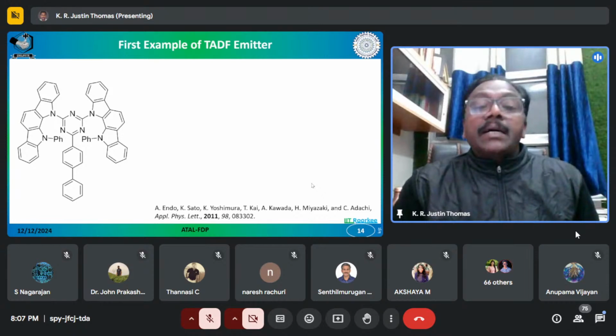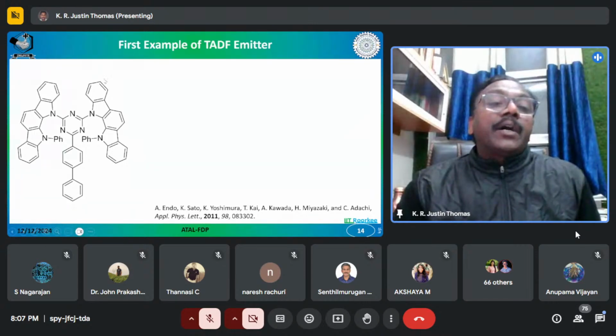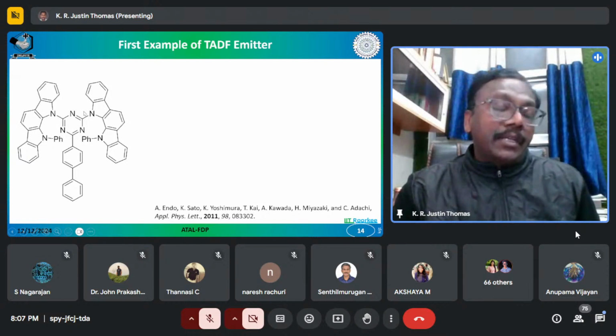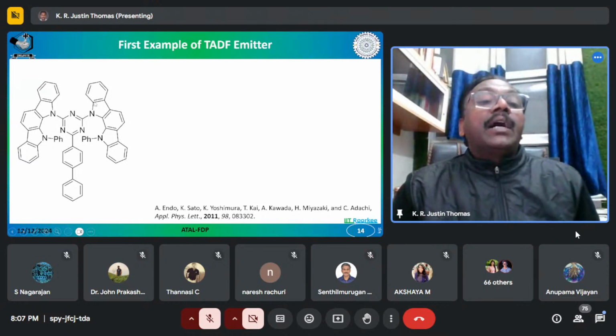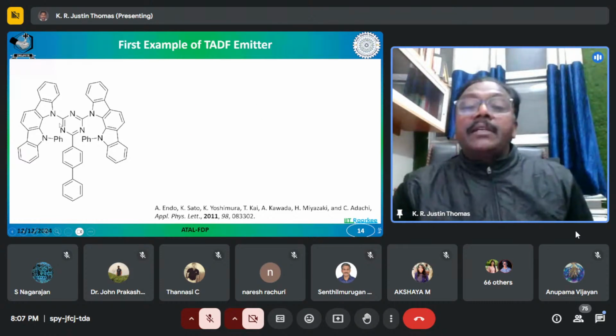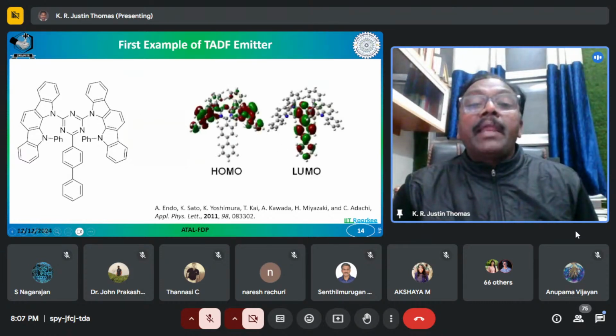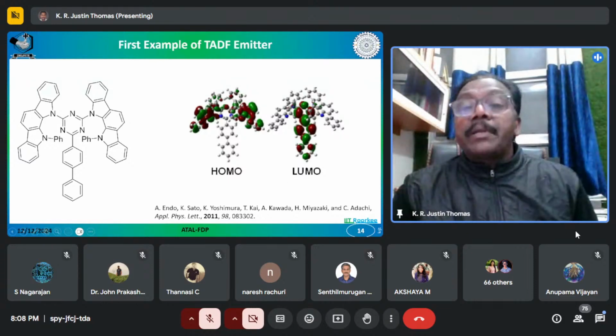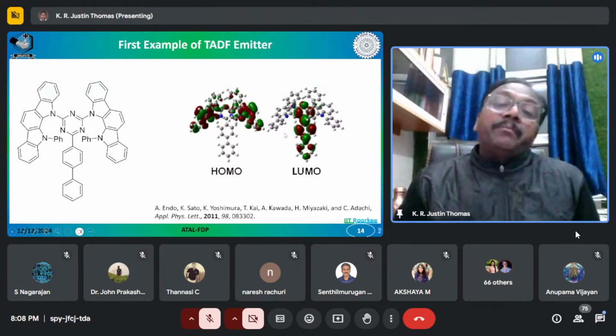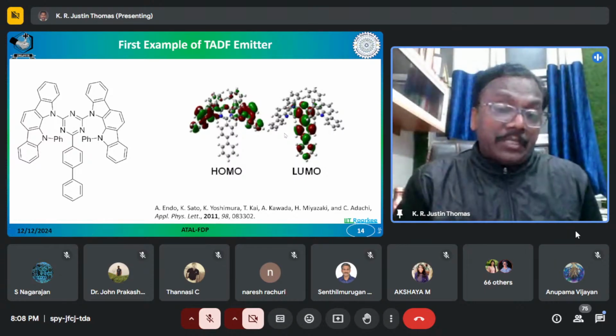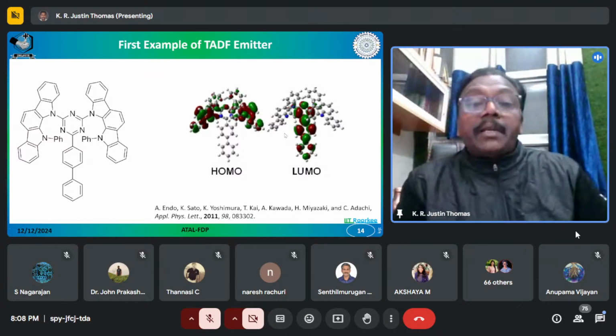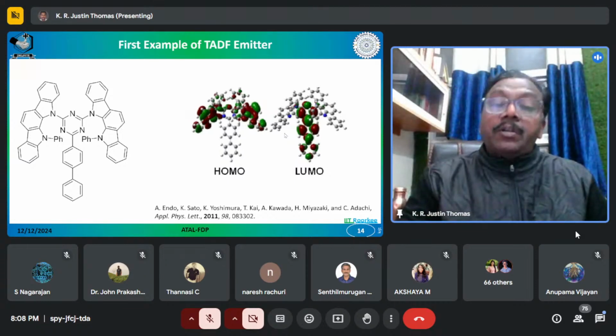This is one of the first examples shown to have a TADF emission. Here you have a donor moiety here, and this is an acceptor moiety. How can you confirm this? You can do a theoretical calculation and see the organization of the HOMO and LUMO. When you do the calculation, you find that the HOMO is mainly on this donor part, and the LUMO is mainly on the acceptor part. There is a very good separation of HOMO and LUMO. So this is one of the first criteria required: you have a donor-acceptor structure, and the HOMO and LUMO are well separated. So the delta EST will be very small.